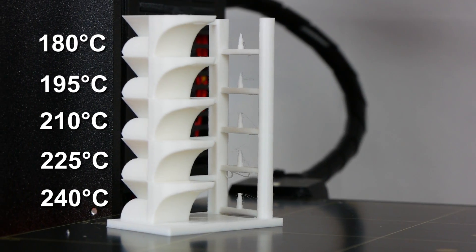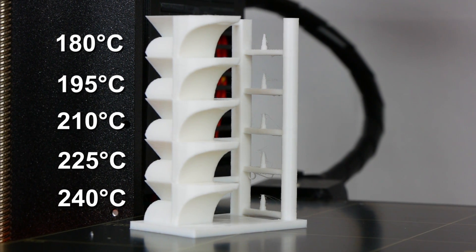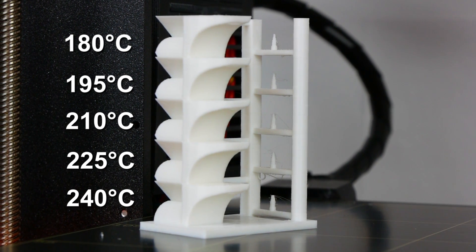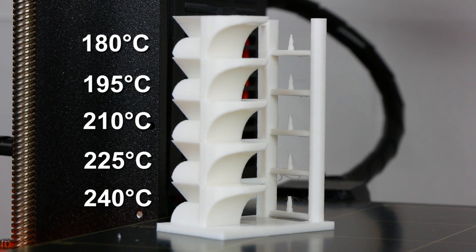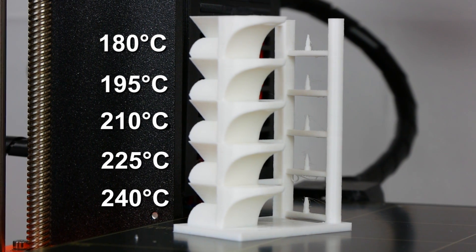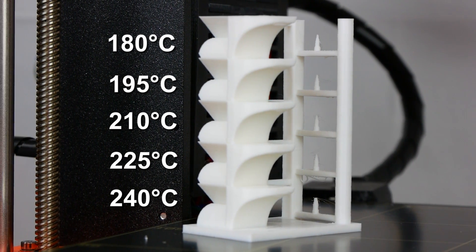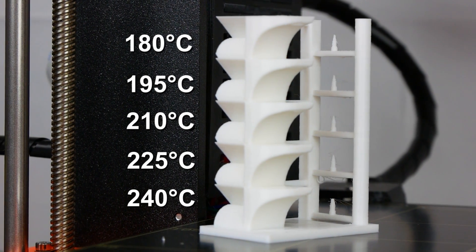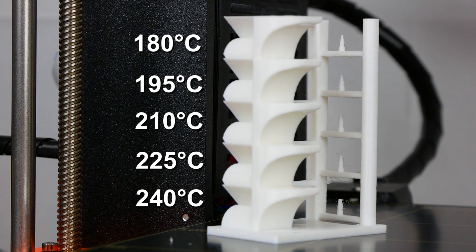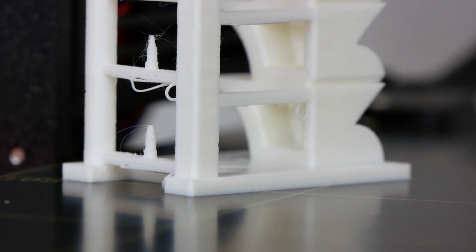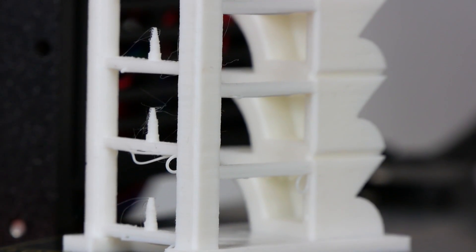I also tested the strength of BQ's white PLA for 180 degrees and 240 degrees. The interesting thing with this material was that it performed way worse with my temperature tower test. 240 degrees showed horrible bridging and stringing, and even at 225 degrees the print wasn't perfectly good. So there you see that even though you might get better strength at higher temperatures, the material itself is just not suitable for temperatures above 220 degrees.